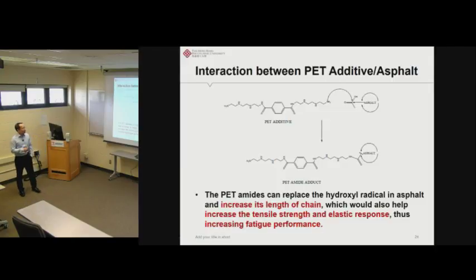If we add the PET additive, the amide groups can again attack this hydroxyl radical in the asphalt binder and replace them. After such a replacement, we can see the length of the chain of our asphalt binder is increased, because originally it just has a hydroxyl radical group like this.